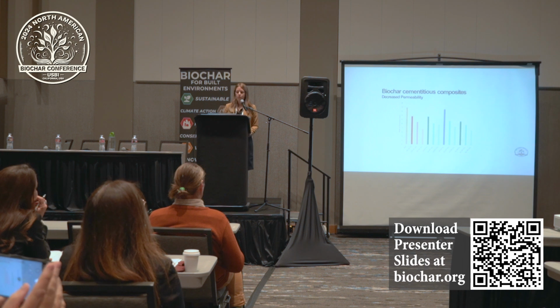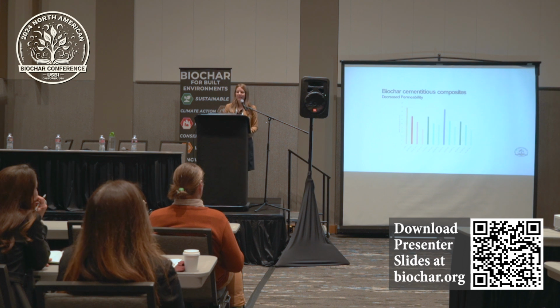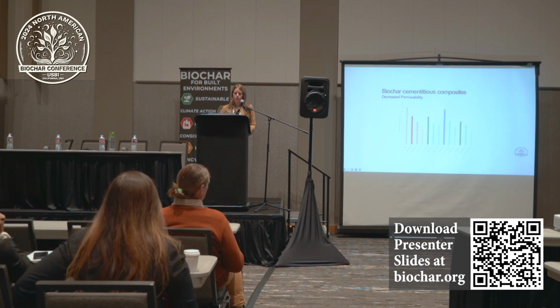So on the furthest left bar here is our control sample. So that is just a traditional concrete. These are actually concrete samples. And we found a depth of water penetration of 18 millimeters. When we add biochar, we consistently see a decrease in permeability. So from left to right, we'll see there's 4 different